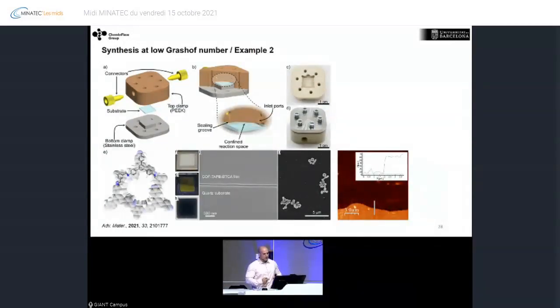Okay. What we also did is the synthesis of covalent organic frameworks. We use the same conditions that we use in the lab in this other microfluidic device. If we do the synthesis in the lab, what we have is the formation of these microcrystalline particles of the COF. But if we do the synthesis under this simulated microgravity using the same conditions, only the controlled diffusion that I've shown before, we have the perfect formation of these really long extended COF films. So this clearly shows you that this simulated microgravity also allows you to control morphogenesis. And that's a very nice finding.